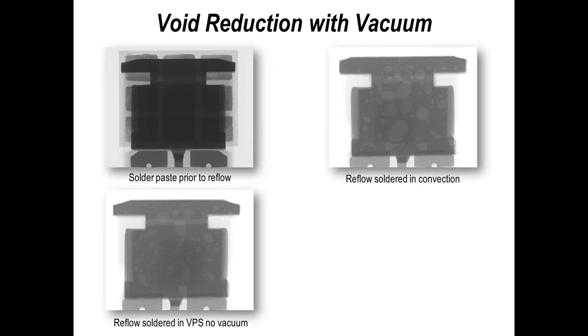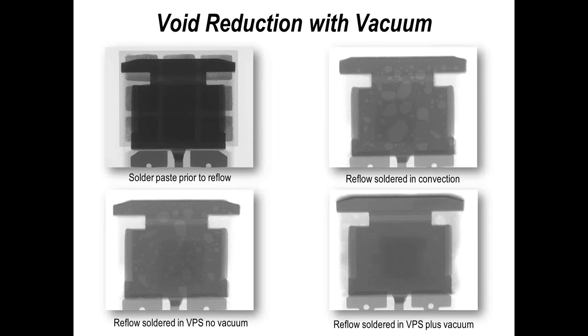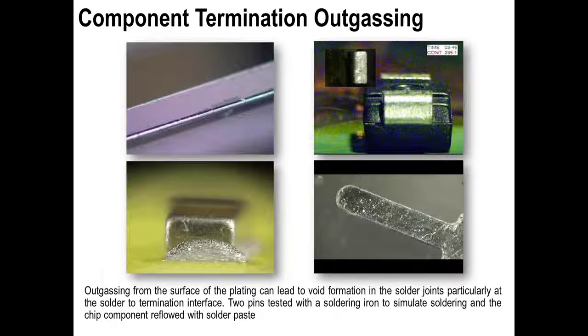But when you use vacuum and use vacuum effectively, what we can do is virtually eliminate the voids, as you see in this fourth example on the bottom right of your screen. So you can see the paste printed. We've broken up the sections, broken up the print area, which is good practice to allow volatile material to escape, and good printing, but we still got voids. Yes, we could optimize the process to reduce the voids to some extent, but at some point you're going to get to the limit of what you can do and the limit you can achieve with a brand of solder paste. Yes, you could change and go to somebody else's paste, which may give you a marginal improvement, but using the vacuum will certainly give you more flexibility in manufacture to reduce void formation.